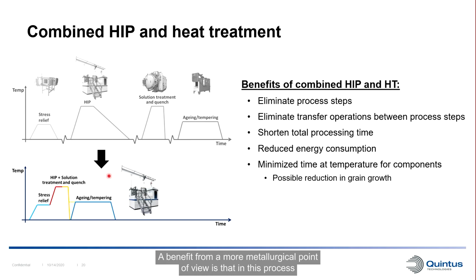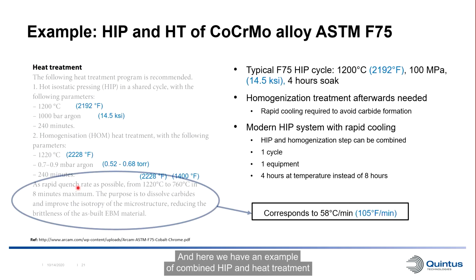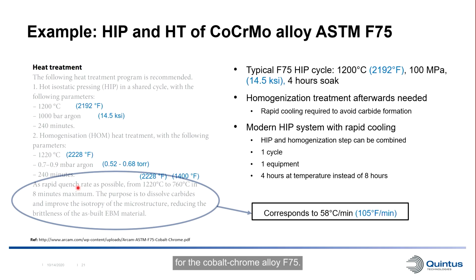A benefit from a more metallurgical point of view is that in this process we are minimizing the time at elevated temperature, which can be important for minimizing grain growth in the material. And here we have an example of combined HIP and heat treatment for the cobalt chrome alloy F75.